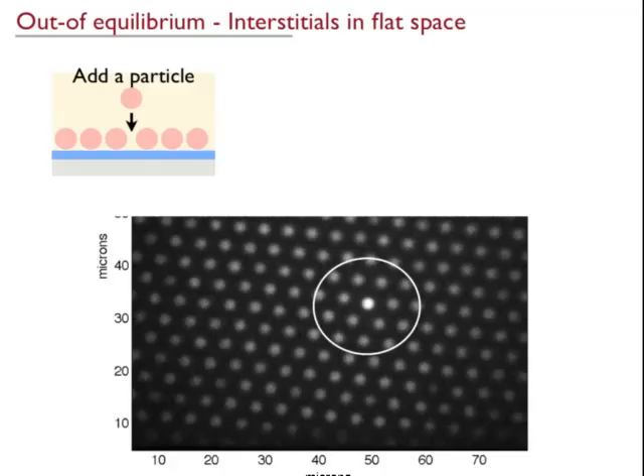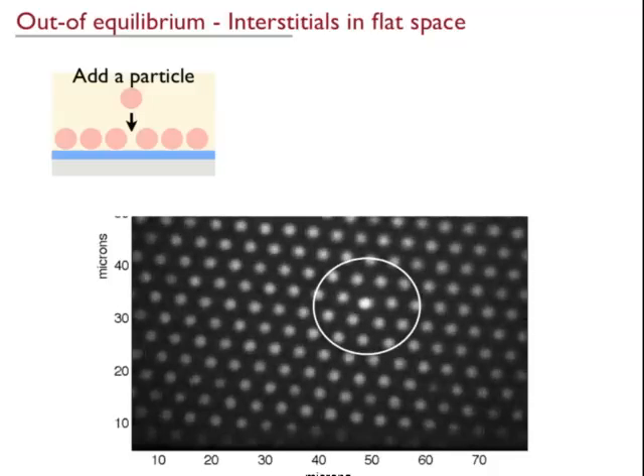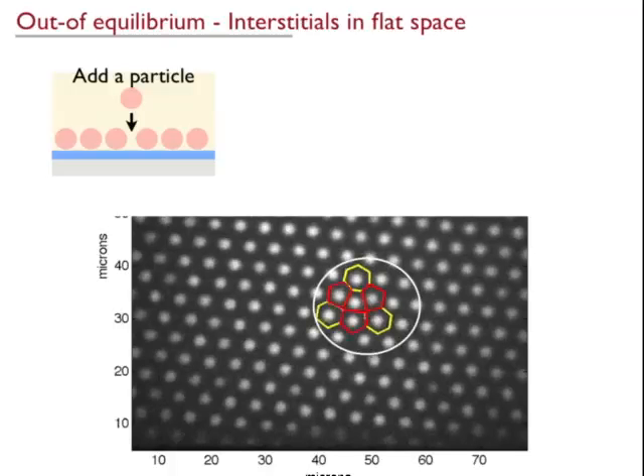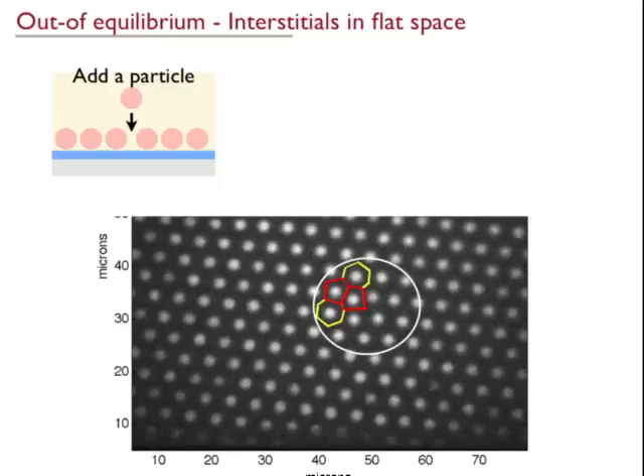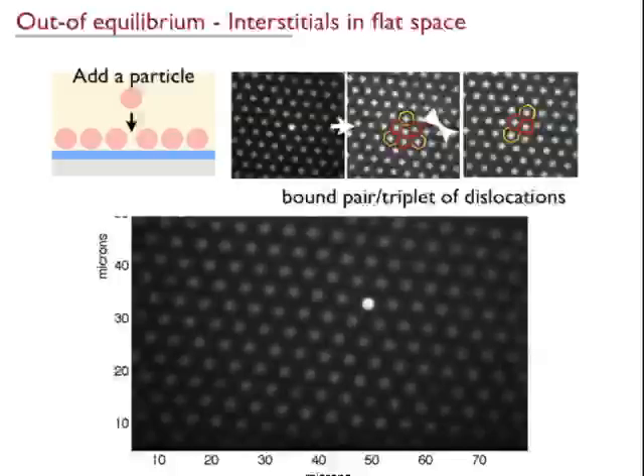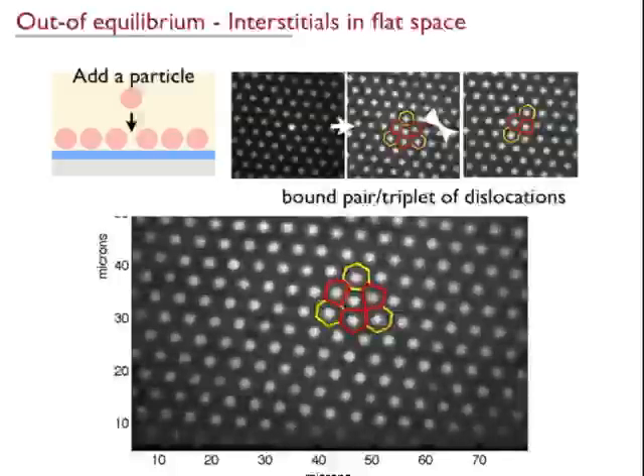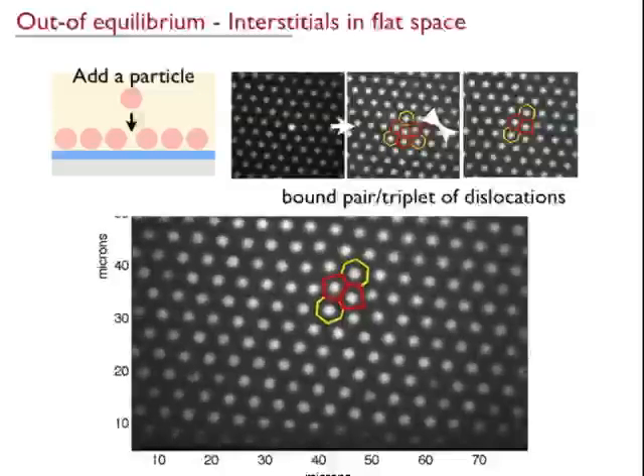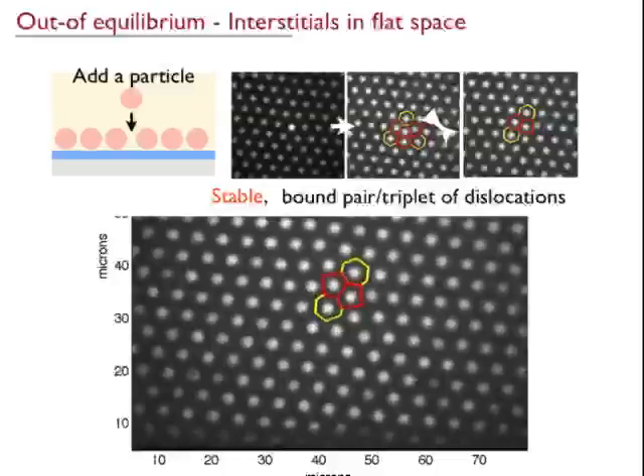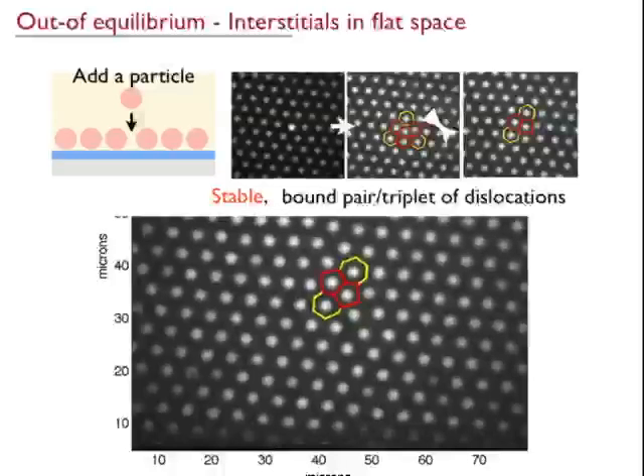So here's adding one to a flat surface. And sure enough, on a flat surface it goes in interstitially, and if you like, it makes 2 or 3 opposite dislocations. So there's no topological charge, and the Burgers vectors add up to 0. That's what it's supposed to do. You can look at this for a while and see it diffuses around, and sometimes it's 2, and sometimes it's 3. It's innocuous, it stays there, and it doesn't do anything.